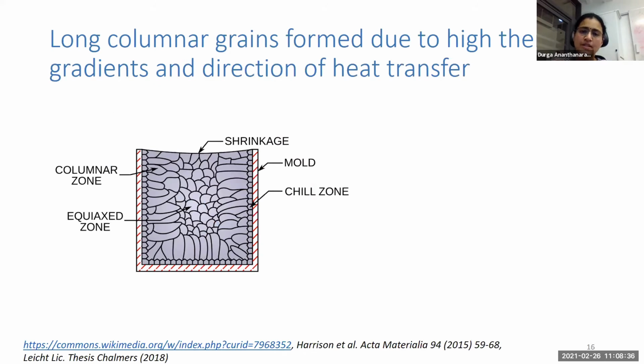So a little bit into what happens during the process, really. So this is an example from casting, which we've all seen in textbooks. So you have the mold and you pour the liquid metal into it. And then from the walls, the solidification starts, and you have columnar grains growing. And with time, the middle portion of the liquid as well cools, and you have sufficient undercooling for homogeneous nucleation, and equiaxed grains form from here. And this is the kind of structure that we get.